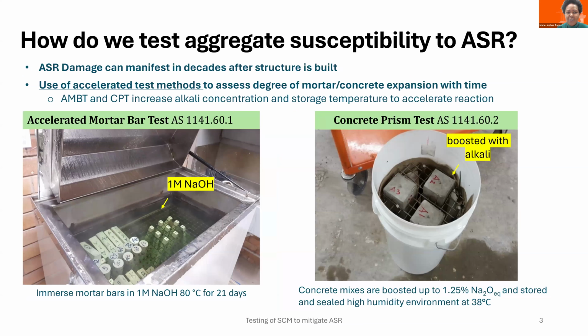Since ASR is primarily caused by the use of reactive aggregate, the best way to avoid having to deal with ASR in the future is to avoid the use of reactive aggregate. Then how do we test the susceptibility of the aggregate to alkali silica reaction? ASR damage can manifest decades after a structure is built, 20 years or more, right? But we don't have that long to wait. So we have to know now, before we actually use the aggregate, whether it has a potential for alkali silica reaction.